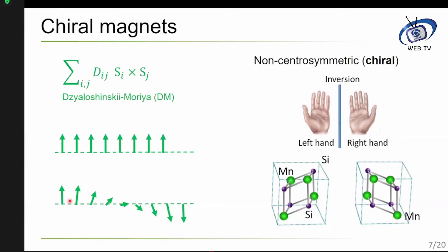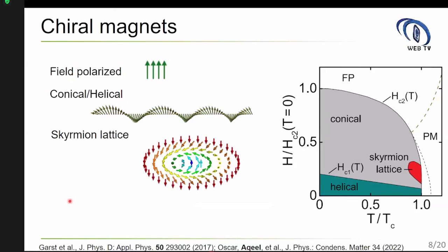If you look at the phase diagram, it is usually not shown for normal magnetic materials because there is only the ferromagnetic phase and the paramagnetic phase. But here there is a very colorful phase diagram. At large magnetic field, below the Curie temperature, everything aligns along the applied field direction and is field polarized, just like normal magnets. Nothing special. But as you reduce the applied magnetic field, the moments start to twist away from the field. And in this small pocket, the red one, the skyrmion lattice, you get a very twisted structure with a round orientation of magnetic moments, and they are very special. I will tell you now why they are special.